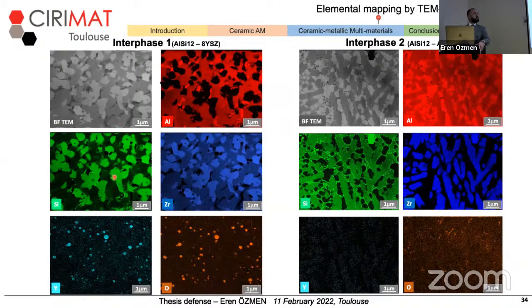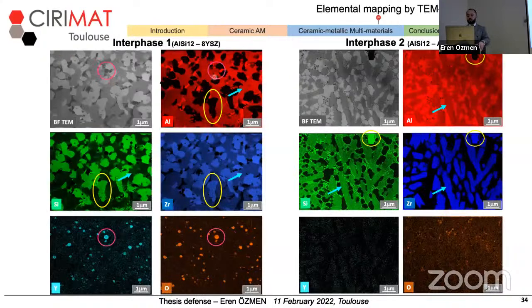And for the two interfaces shown side by side, we can see the intermetallic phase between zirconium and silicon, where only silicon and zirconium appear, but aluminum does not appear in both interfaces. And the ternary phase, as all three of them, silicon, zirconium, and aluminum, appear in two structures. However, there were some point-shaped areas observed where there is aluminum, oxygen, and yttrium, which were indicated with pink circles. The composition and situation of these circles was still a question mark.